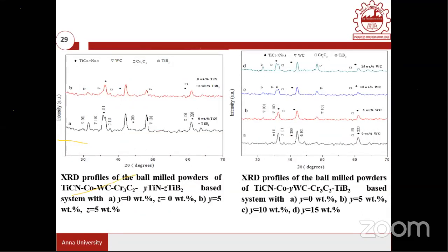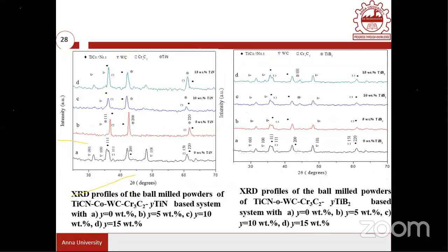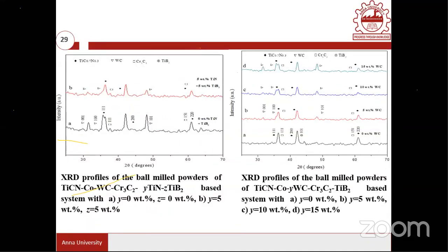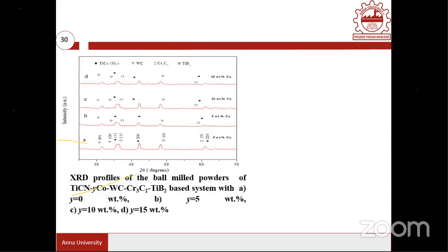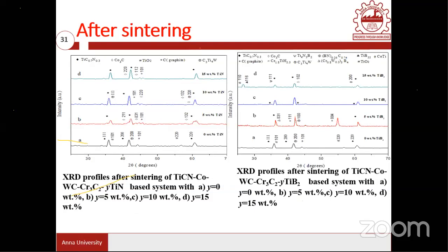So these are the compositions. In the first case, titanium nitride is a variable. In the second case, nano titanium diboride is a variable. In the third case, we are varying titanium nitride and titanium diboride equally. In the fourth case, tungsten carbide is variable, and finally the cobalt is a variable. So five variations, five compositions, and these compositions are sintered by spark plasma sintering.